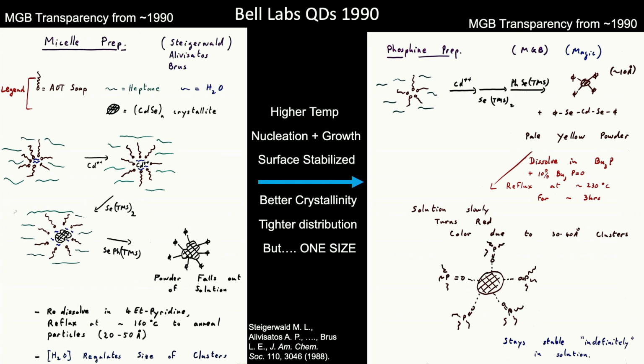And Steigerwald's genius was that, well, this is still an active surface, so we can follow that up with a phenylselenide coating. And with the phenyl groups now on the surface, this is no longer water-soluble, water-dispersible. So it comes out of the bubble and it's not particularly dispersible in the hexane either. So it falls out as a powder out of solution. That was a really great discovery, this particular synthesis. Then they realized, well, this crystal structure is really terrible. Room temperature, you're not going to form a good crystal. So they decided to anneal these things to increase the crystallinity. And that's where they used the pyridines, in this case at 160 degrees.